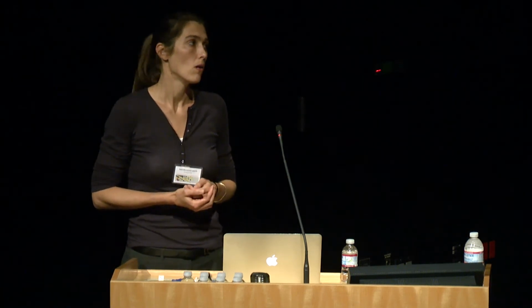So your sensitivity goes as the square root of N, the number of NV centers that you have. Actually, another kind of big problem is that the conversion ratio of nitrogen to nitrogen vacancy centers is not 100%. So if you keep adding more nitrogen, you stop winning after a point.